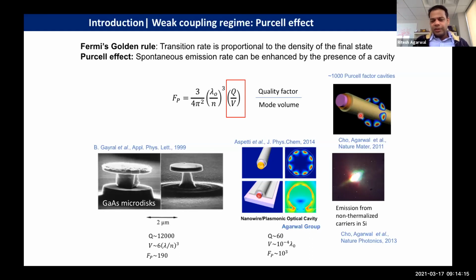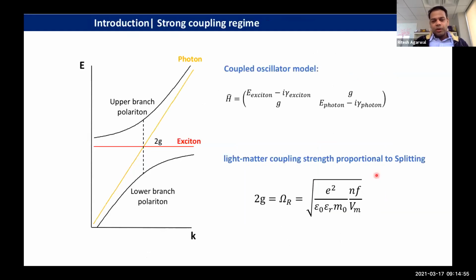So they were violating, from molecular spectroscopy, this idea of Kasha's rule. The emission was not taking place from the lowest excited state; even before the system could thermalize in the excited state, the system was forced to emit. After demonstrating that, we applied this idea to a material like silicon, which does not emit light in the bulk regime, and we were able to make silicon emit light with an internal quantum efficiency of the order of 1%. So this shows that by engineering light-matter interaction, even in the weak coupling regime, one can get very interesting properties. And so we did quite a bit of work on that.